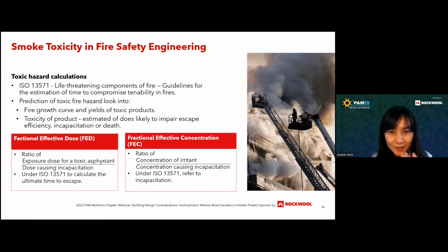So how do you determine smoke toxicity? Two ways, based on ISO 13571. First is what we call FED, fractional effective dose. This FED is based on the asphyxiant gases. When we say asphyxiant gases, it is something that causes hypoxia, meaning a decrease in the oxygen supply, in a way causing the occupant to lose consciousness and leading to death. The gases are carbon monoxide, hydrogen cyanide, and so on. The formula is the exposure dose for a toxic asphyxiant over the dose causing incapacitation.